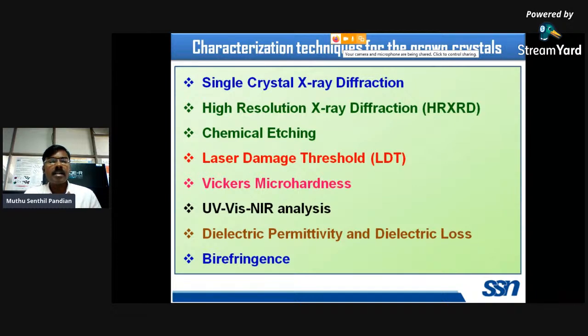In order to identify the structural properties of the grown crystal, we have used this single crystal X-ray diffraction measurement. And to identify the crystalline perfection of the grown crystal, high resolution X-ray diffraction measurement was performed. To identify the dislocation density of the grown crystal, chemical etching measurement was performed. So in order to identify the laser damage threshold for a laser application like KDP or other material, one must know the laser damage threshold value of the grown crystals. So under identical condition, we have performed all this characterization. To identify the mechanical property of the grown crystals, microhardness measurement was performed. To identify the optical property of the grown crystals, UV-visible measurement was performed. Electrical properties, dielectric permittivity and dielectric loss, and to identify the optical homogeneity, Birefringence measurement was performed.